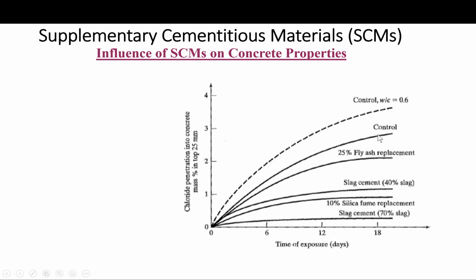You can see this is the control mix, and this is the control mix with higher water cement ratio, which is even worse. Look what happened when we add SCMs with 25% fly ash replacement - definitely there is a decrease.